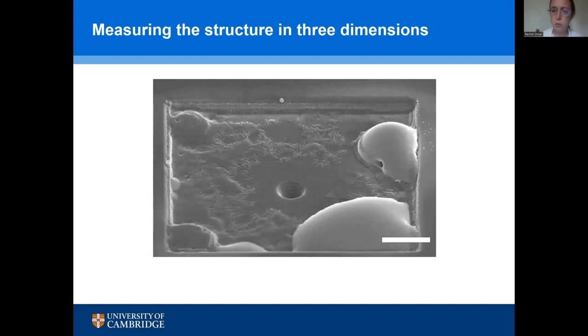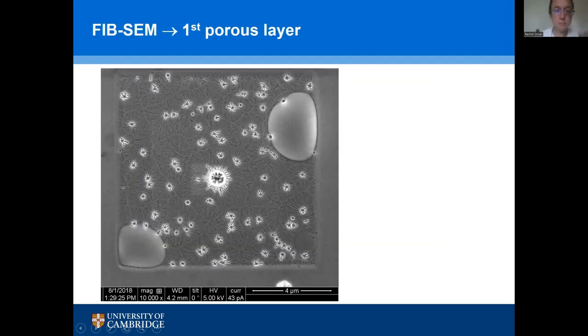It gets more and more spoilt by these large gallium droplets. So we only managed to mill down through about 5 layers. Then we can take those images, which were taken at a slight angle, and process them so it's as if we're looking straight down from the top, and look at the porous layer in the SEM. We're seeing some quite similar features to what we saw in the TEM. It's a bit damaged by the whole focused ion beam milling process.